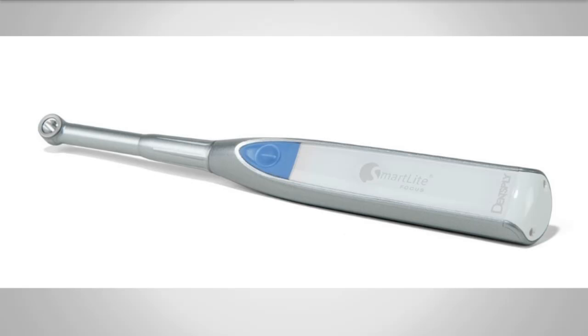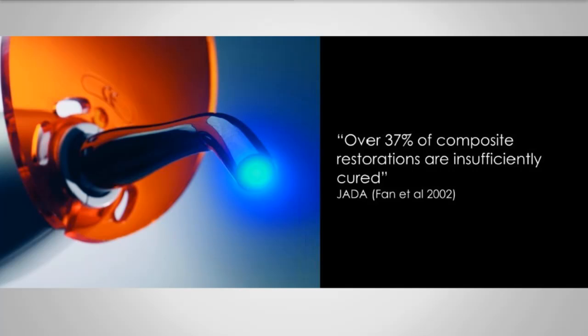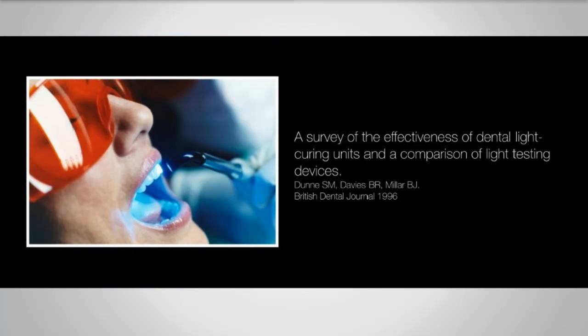I think the most important thing is to buy a good quality light cure unit that you're sure of the source, that you know that it's got a decent power output of 1,000 milliwatts per centimetre squared or more. So something like the Smart Light from Dentsply. This study found in 2002 concluded that 37%, that's an awful lot of composite restorations, were insufficiently cured. And Dunne and Millar in the British Dental Journal back in 1996, they did a survey of light curing units, and they also found that dentists were under curing composites. And this was for a variety of reasons.